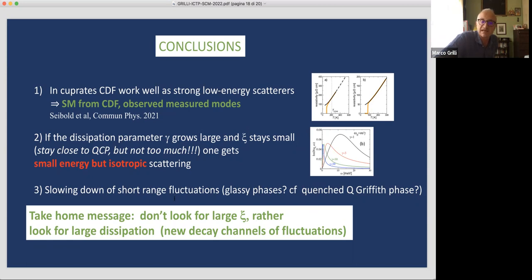So the take-home message overall is that in order to find a consistent description of the strange metal behavior, we not necessarily have to go to the quantum critical point, but we should rather stay away, so that the large xi is not attained and we keep gamma xi finite, but we look rather for larger dissipation. So this is the message I would like to convey to you.